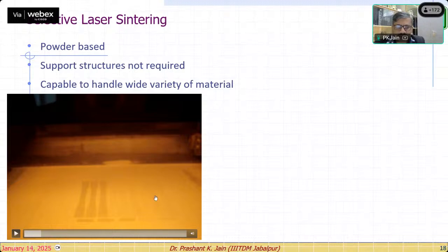You can see over here, this is the powder bed and the tensile specimens are fabricated. Just because we have conducted this experiment with nanoclay, we can see some reflection of the laser beam while it is coming on the polymer material, otherwise it is fully absorbed. The laser heat is absorbed by the polymer material, and here you can see the solidification is done. On both sides you will see the recoaters. The recoater will spread the powder and the infrared heaters will be switched on to keep the entire build chamber just 4-5 degrees centigrade below the melting temperature of the polymer.